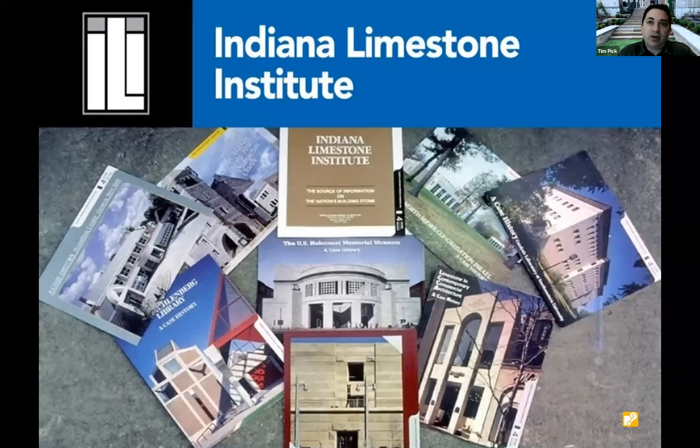The stone was delivered over a 2-year period, and it was installed at different times, some in the summer, some in the winter. So the stone needed a season on site. So it looked like a checkerboard in the beginning. And so we brought the Indiana Limestone Institute in, and they said, no, not a problem. We understand what's going on. The stone is seasoning since it's installed at different time periods using stone from different areas of the quarry. In different cutting times, there's a lot of different moisture that's coming out of the stone.